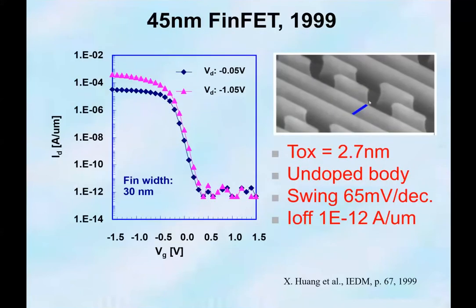But in the same year, 1999, and this is what Saeed mentioned, the Berkeley device group published this IEDM paper showing that already we can make 45 nanometer with better subthreshold swing and much better leakage current than the production 130 nanometer transistor. And we didn't use half a nanometer of oxide, we just used 2.7 nanometer oxynitride. We don't even need heavy doping to stop the leakage current or punch through, or ultra shallow retrograde doping. We don't need any doping to control the leakage, and that's what FinFET can do.